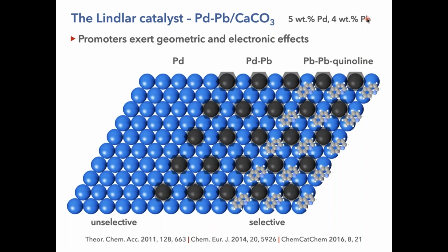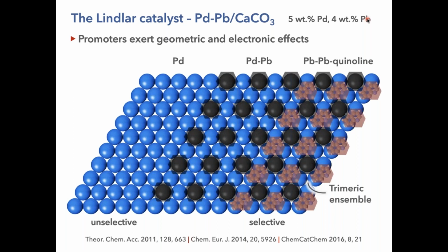Those studies ended up in this very beautiful picture that shows that actually when you alloy palladium with lead and additionally you adsorb quinoline on the surface, you form these trimeric ensembles which are very selective because they are enough to activate hydrogen and to proceed with the hydrogenation, but not so active in promoting hydride formation, which will actually decrease the selectivity. So you will actually end up hydrogenating the triple bond towards the double bond.